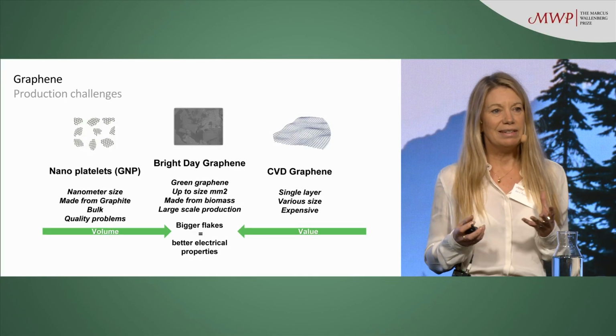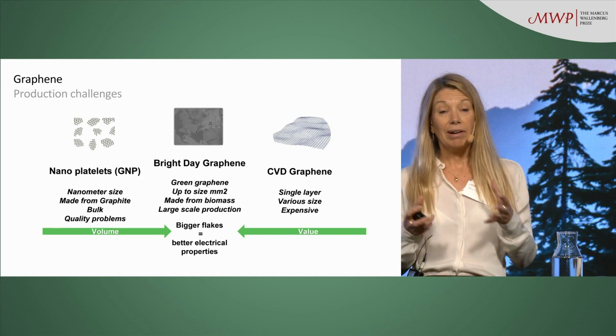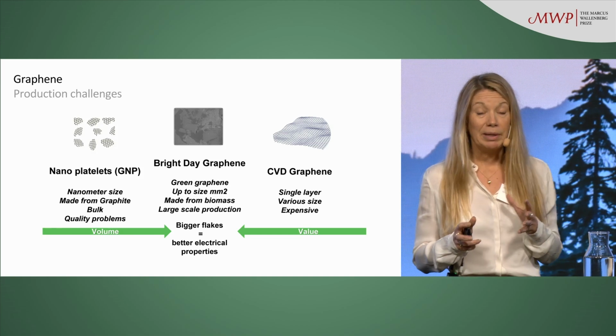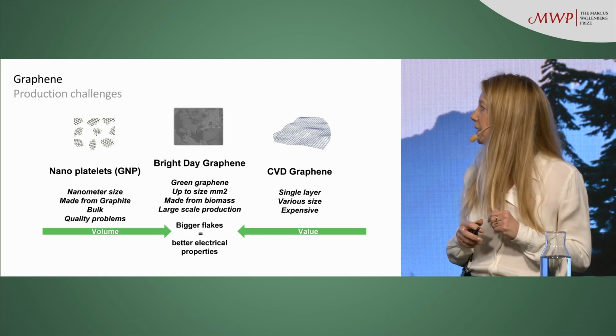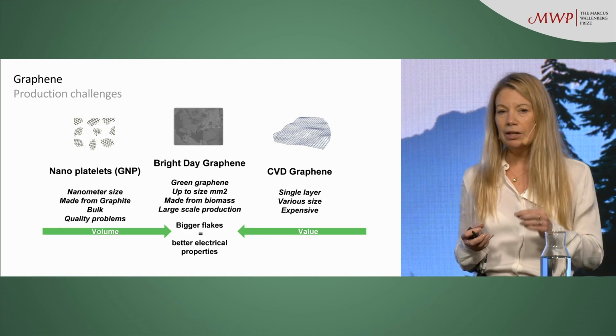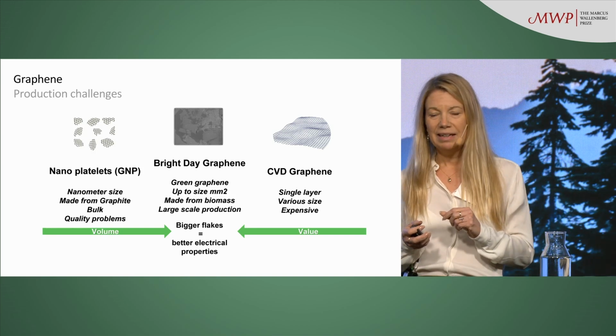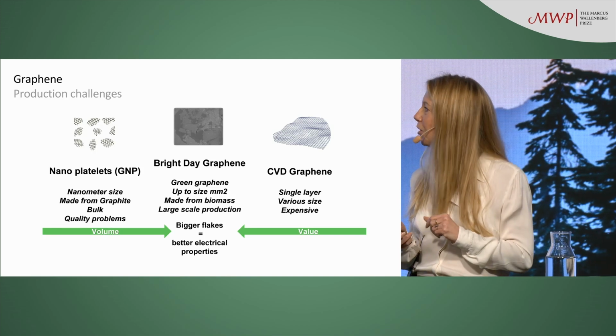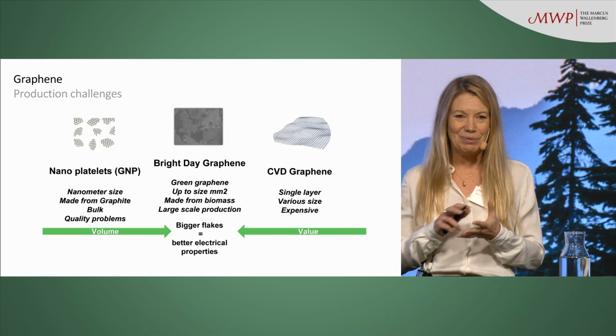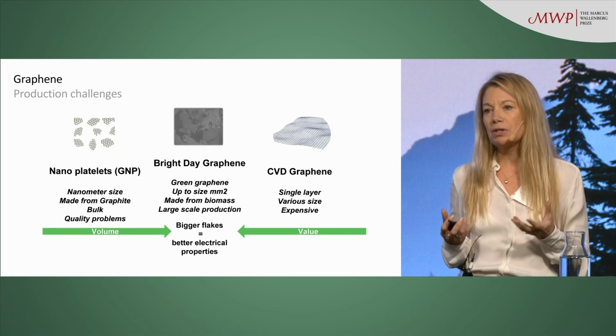And the other method is the graphene nanoplatelets, where you take graphite and exfoliate it mechanically or electrochemically into a graphene powder. You get nano-sized flakes that are often a bit thicker, not a one atom layer. And this means that you lose a lot of the properties that are so fantastic about graphene, especially the electrical properties. So what we wanted to do was to make another kind of graphene. It's still a graphene powder, but with larger and thinner flakes, which gives it more of the electrical properties.